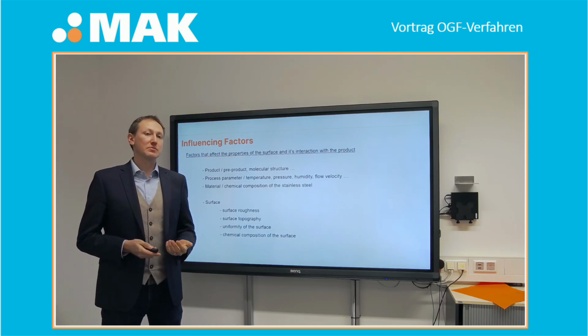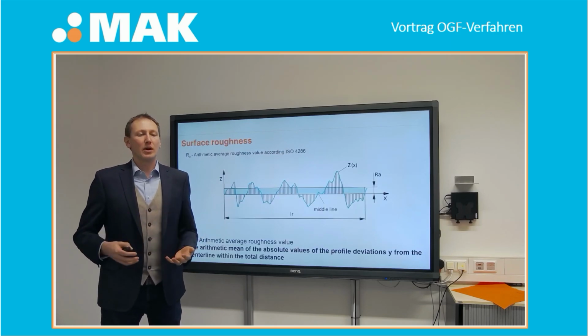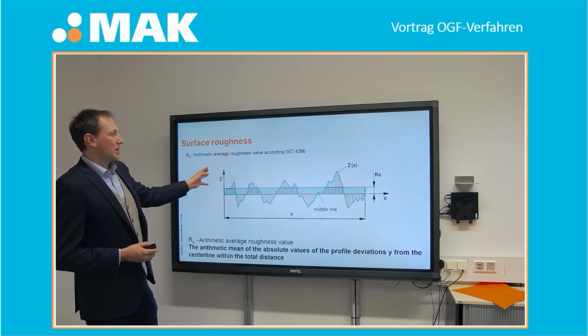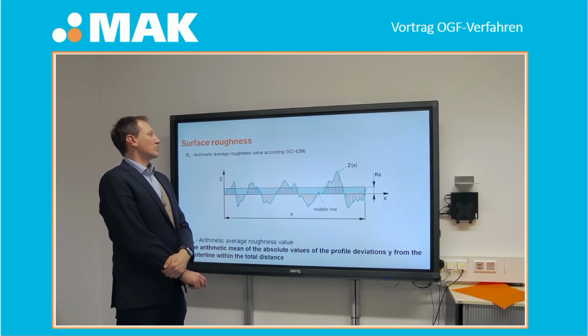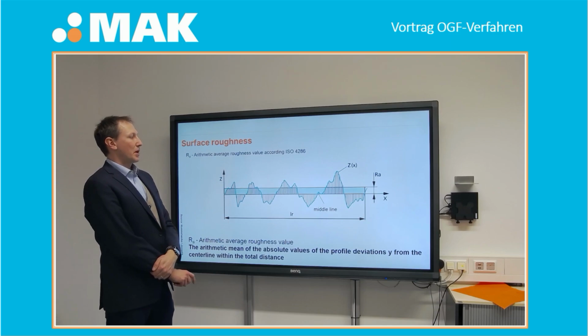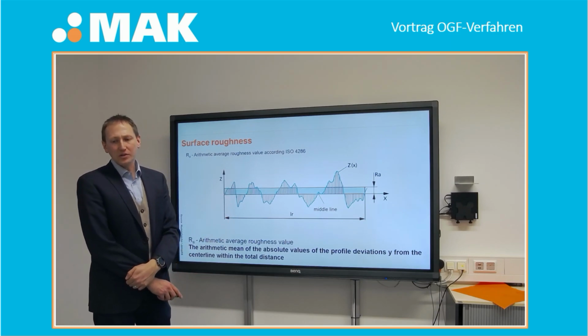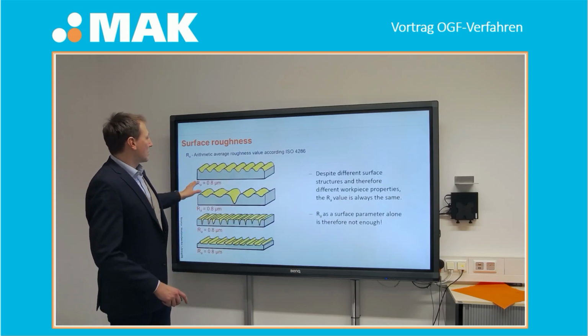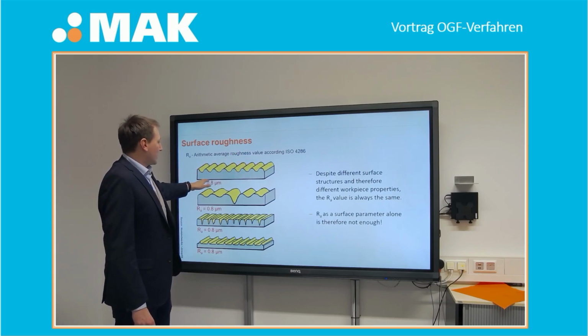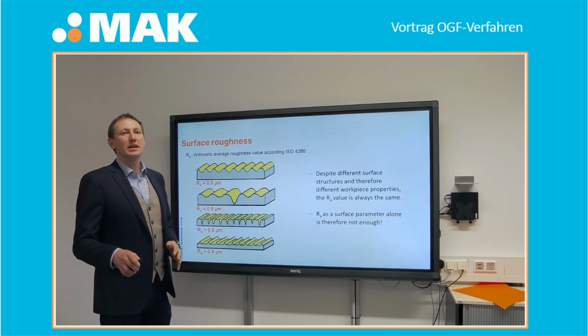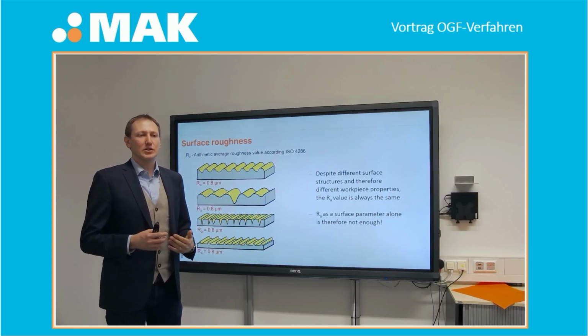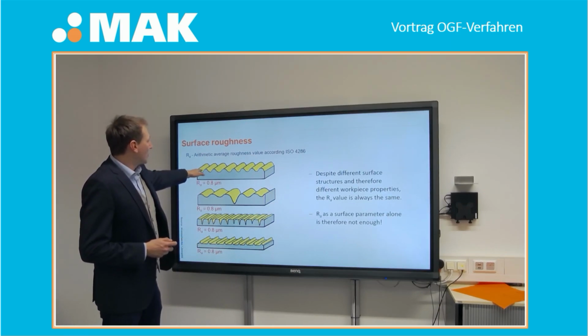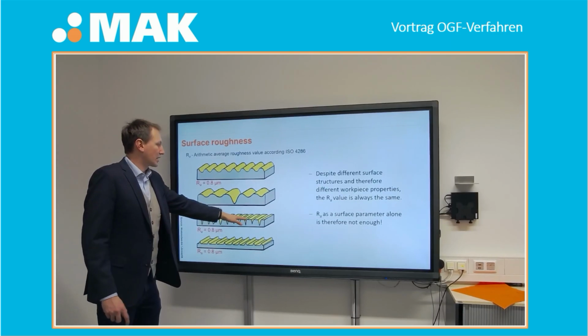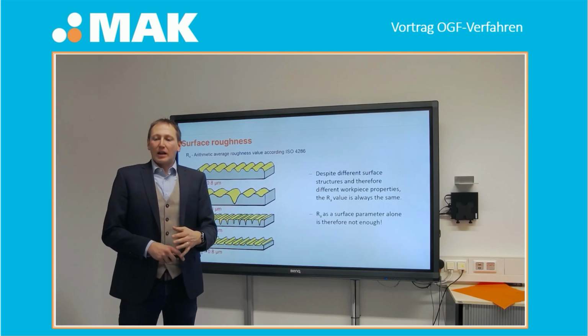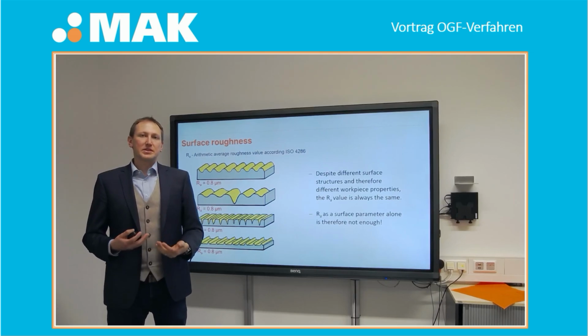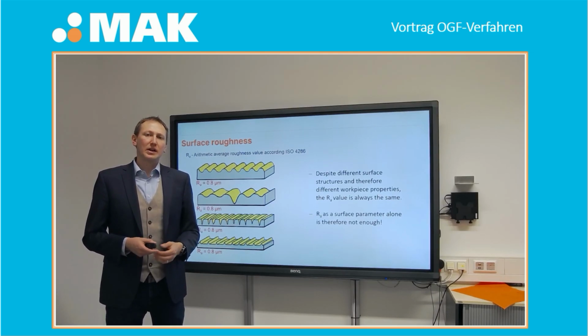And if we're talking about surface, we also have to talk about surface roughness. I guess it's well known that we have different standards to characterize surface roughness, for example the ISO standard 4287 to characterize surface roughness by the Ra value. And it's also known by many people that a surface roughness like Ra 0.8 micrometers can lead to very, very different surface topographies. Like shown here, you can have a very nice homogeneous structure, but you can also have a structure like this or like this. So even if we have a standard surface roughness smaller than 0.8 micrometers, we must be aware that you can have completely different surface conditions.